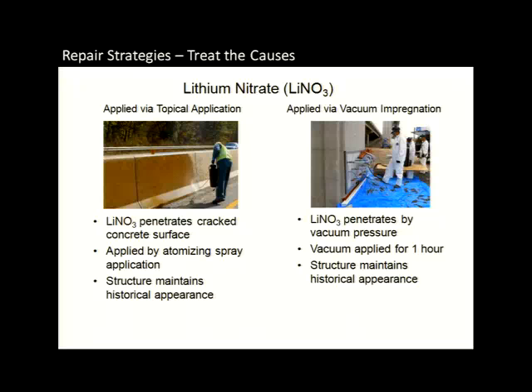And the manufacturer selling this said, a number of years ago, this was a very effective way to control and mitigate ASR. What they'd shown was that in the laboratory, if you took small specimens, submerged it in the lithium nitrate solution, you can pretty much arrest ASR from happening because the lithium is very easily able to absorb into a small specimen. It interferes with the structure of the gel and renders it non-expansive, so you end up stopping ASR.